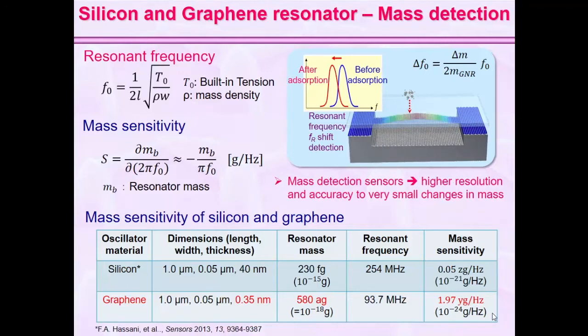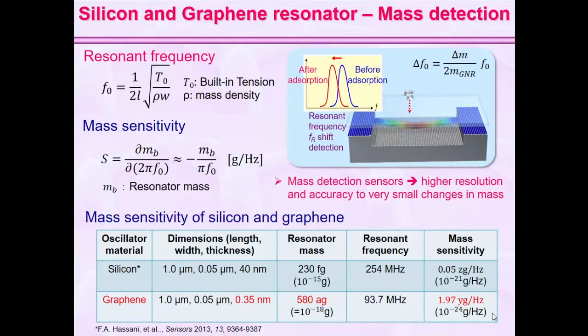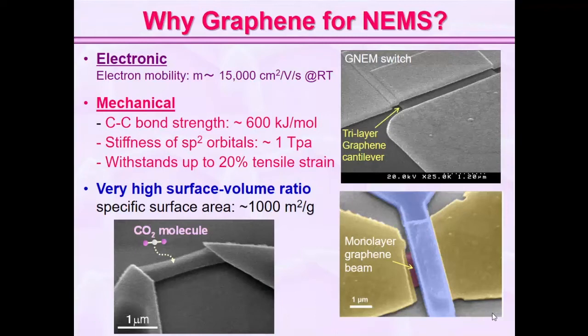If you compare the existing solutions, already developed ones are silicon resonators, and more recently carbon nanotube and graphene resonators have also been developed. The advantage of graphene compared to silicon is that its thickness can be reduced to a monolayer — that's the main thing. This leads to increased mass sensitivity because of its lower weight, and it can increase sensitivity more than 50 times compared to silicon for comparable dimensions. Also, CVD graphene doesn't have the location-control problem that carbon nanotubes have.